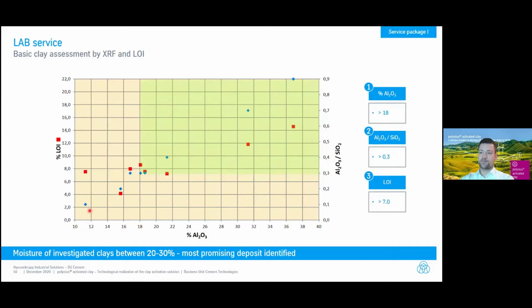This is for sure. So then the other extreme is a very good sample here, for example. So here we can see that the LOI, this is the red one, is around 14–15%, which is fitting, which is good. We see that the alumina to silicon ratio is quite high, which is also good. And we see that the total amount of alumina oxide is above 18%. So we are in the green region, which is giving us the indication, first of all, that this is a very good clay. So we have some good clays here, 2 samples.